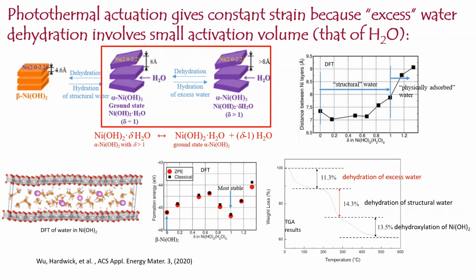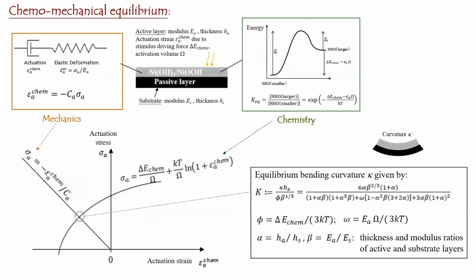So if you remove water molecules one by one, each water molecule has a very small volume. So the activation volume is very small compared to the electrochemical actuation, where I said that because of the cation insertion and the structure change, the activation volume was large. Here, the activation volume is small, and therefore the behavior gives more or less a narrow range of the strain. So the strain is rather narrow. So at least that is the theory right now that we believe.